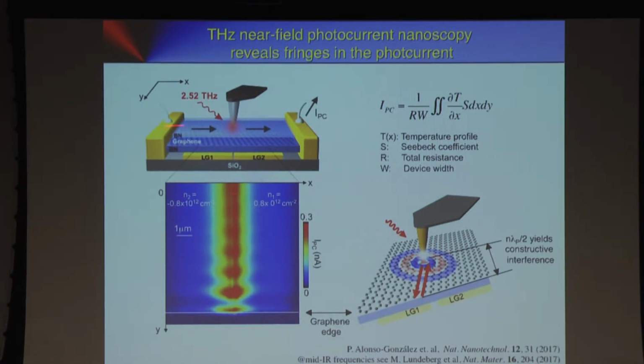So in principle, this device is a terahertz photodetector. But what we detect now is not far-field radiation, but the near-field intensity at the tip apex. And this is the device that we scanned here. And what we see here is a photocurrent image. So the photons come in here and create a current, then we scan and we get this photocurrent map. And we get an amazing signal to noise here because we directly detect the near field. We don't need to go back to the far field. And this is one possibility to increase the sensitivity. That may also be interesting with synchrotron radiation.